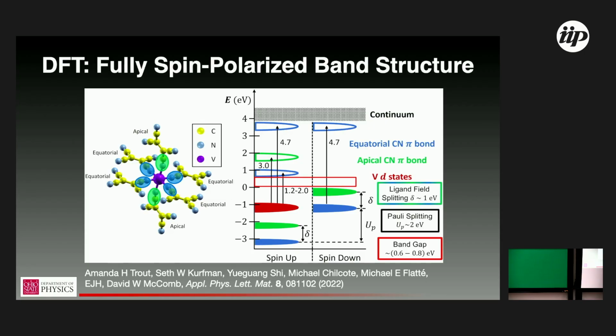The other is the difference between equatorial and apical. You can see that also is a pretty large energy scale. So these different TCNE groups are behaving very differently. And if I want to use the language of magnetism, this would lead me to expect some strong crystal field interactions, basically some crystalline anisotropy in the system, which we have observed. So this is fully consistent. And then the red states are the vanadium d orbital, and I should have mentioned earlier this is a ferrimagnet. So we have spin up on the central vanadium of 3/2, and then spin down of 1/2 on the TCNEs, which the stoichiometry gives you a net excess moment of spin 1/2 for the unit cell.